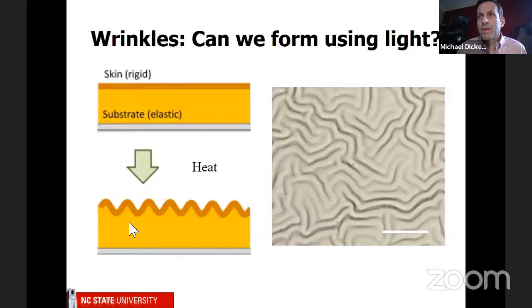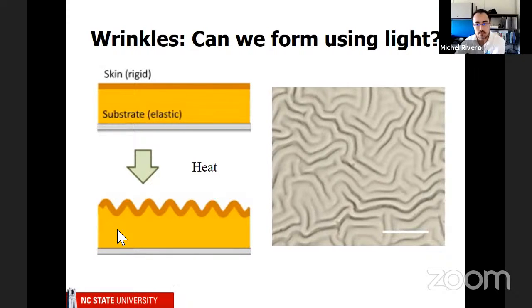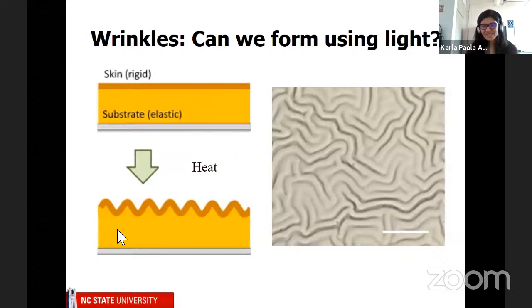If you think about what's happening, you're doing two things that are in competition with each other. One is you're bending these films, which is dictated by its modulus and its thickness. And then you're also distorting the underlying elastic material, so there's also some elastic energy. I'm sorry, I don't remember the exact scaling relationship, but it's something like the ratio of the modulus to either the 1/2 or 1/3 power multiplied times the thickness, and that gives you a rough approximation of the periodicity. So it's not a perfect model, but it's a scaling relationship. Okay, thank you. Great question. Thank you.